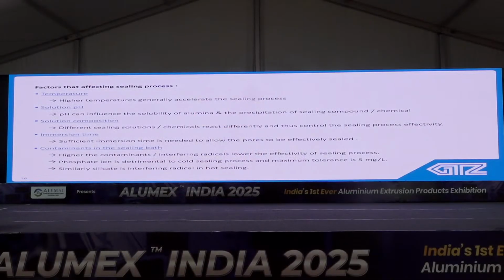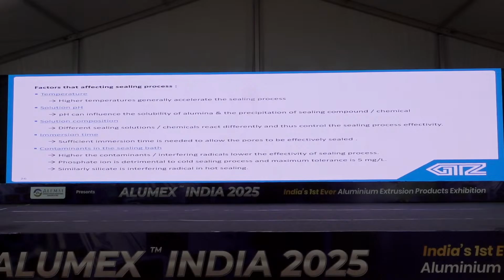So now I will be discussing in detail different types of sealing and their mechanisms. Why is sealing required? It improves the corrosion resistance, enhances aesthetics, reduces dye leaching if it is dyed after anodizing, and prevents the ingress of corrosive material and contamination into the anodizing layer. These are the sealing parameters: temperature, solution pH, solution composition, immersion time, and control of contaminant level in the sealing bath. Phosphate is the most detrimental impurity, and the maximum limit is only 5 mg per liter.